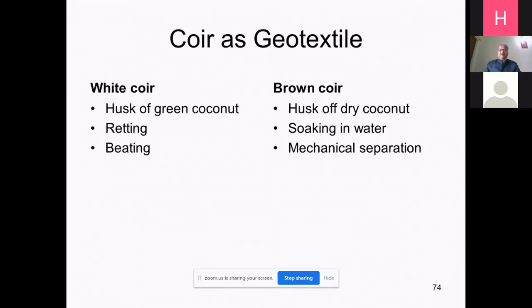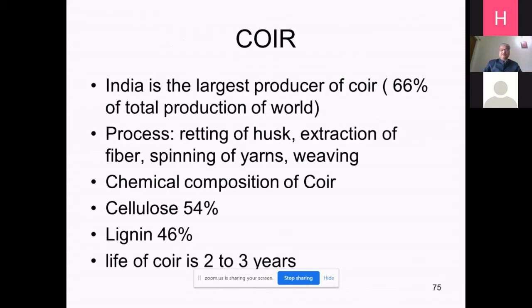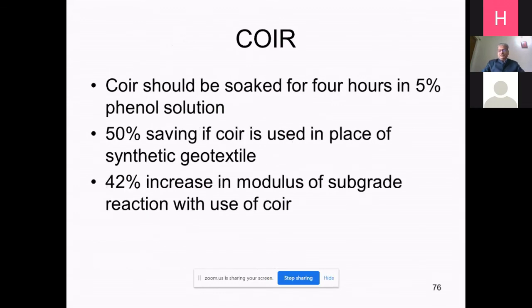Then coir, as I said, is available in all the coastal regions, and it can be taken from the white coconut as well as from the green coconut. White coir is made from the green coconut by retting and beating, while brown coir comes from the weathered coconut, and then the coir is separated mechanically. The chemical composition of coir is 54% cellulose and 46% lignin. It should be soaked for 4 hours in a 5% phenol solution, and a 50% saving is there if coir is used in place of synthetic geotextile.